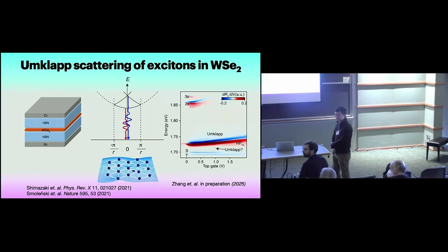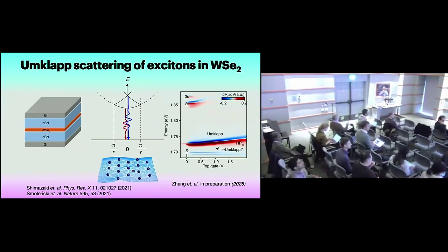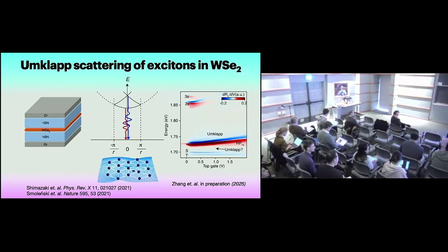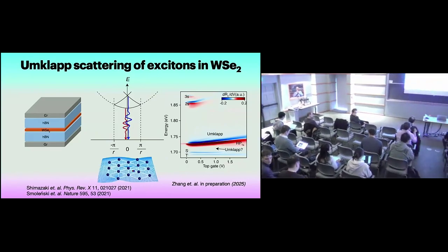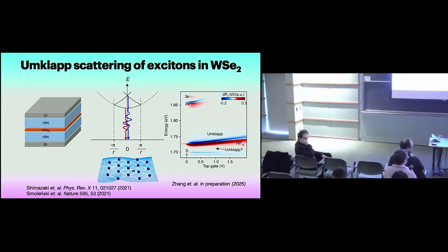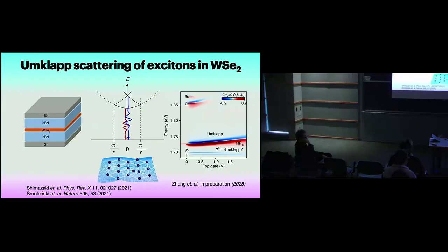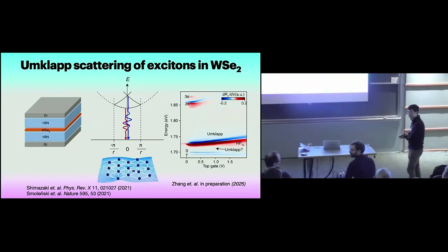So if there's any variation in the Wigner crystal period from site to site, area to area, you'll probably see this broadening in the signal. Do you have any estimate of how narrow the original peak is and how much broadened it is just because you're looking at a large area? Yeah, so that's an excellent question. So it turns out that even for this neutral exciton, we already have broadening due to both inhomogeneous broadening and also just natural broadening from the radiative lifetime.